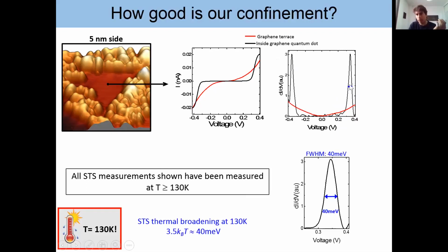And by analyzing the width of those states, we can learn about the lifetime of our quasiparticles and how good our confinement is. But of course, as I was telling you at the beginning, we have to do the modifications. In order to do the patterning, we have to be at high temperatures. We usually do them at 220 Kelvin. Then we try to go to the lowest temperature possible to get the best energy resolution that we can. The best we have achieved is 130 Kelvin. Being able to stay in the same place from 220 to 130 Kelvin is really a challenge, at least for us.